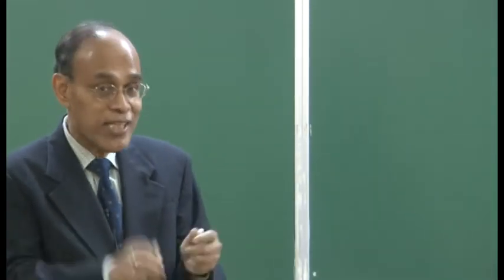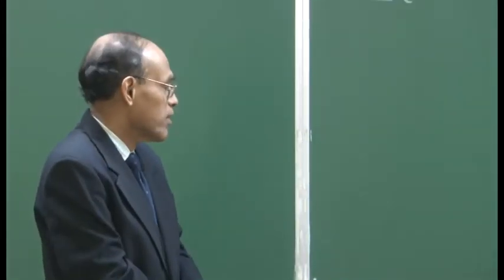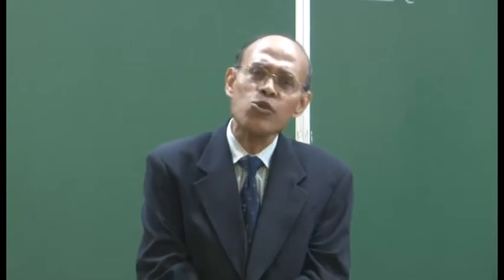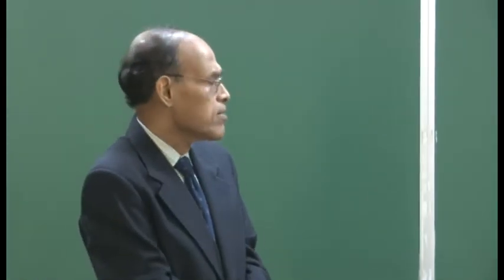On the other hand, we will discuss this point when we study steel making in greater detail, why it is not going to be economic, that point will be clarified in greater detail. Similarly, if silicon content is too small, in that case what happens is we may not get enough heat. So, silicon content is never too small. Okay? Silicon content, because we operate at high temperature in the blast furnace, and also that the gangue material will contain silica. So, therefore, there is a chance of silica getting reduced in the blast furnace, at least partially landing up in the hot metal itself. But most often silicon does not exceed the threshold value.